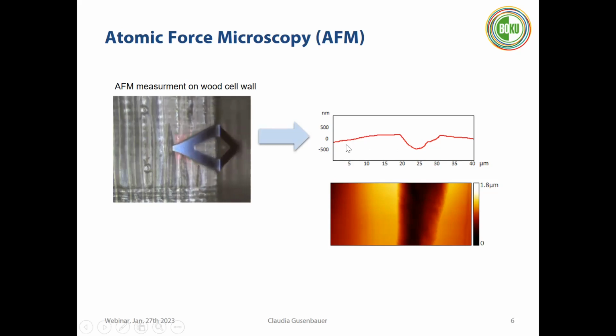And then line by line, you see it on the right side, we generate our image and we create a false color image, which you see on the bottom of the slide. So this false color image gives a representation of the topography of our sample, and is generated in a way that high points will get a bright color and low points will get a dark color.